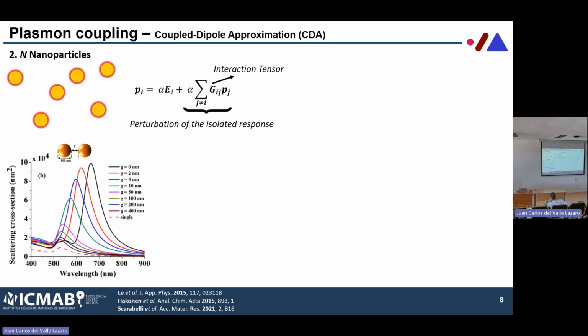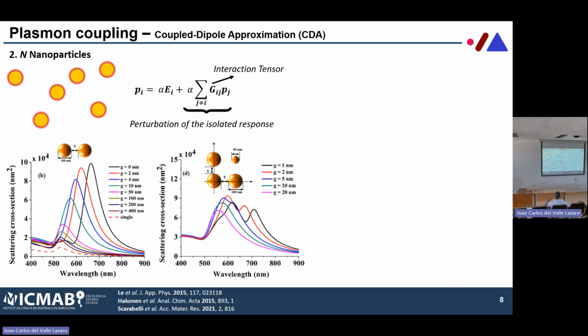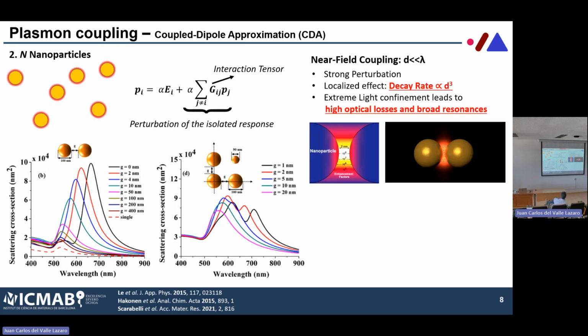Okay. If we analyze this type of system, again, this is all numerical, but it serves very well our purpose here, is that we see that there is an interaction within the particles that depends on the distance between the interacting particles. And if we get very, very close, we see that the response changes dramatically. Okay, I can make a dimer here, but I can make a more complex system. But basically, the take-home message here is that we can identify 2 regimes of interaction.